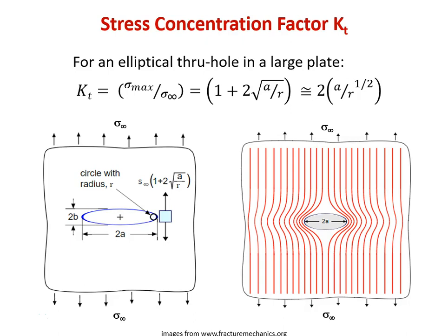So the ratio of the average stress over that whole big thick plate, sigma infinity, to the stress right at the edge of that elliptical hole is defined as K sub T, called the stress concentration factor. That's defined, of course, as sigma max, the stress right next to that tighter radius on the ellipse, over the average stress over the whole plate, sigma infinity. And that's equal to 1 plus 2 times the square root of a, which is the long radius of the ellipse, over r, which is the radius of curvature right at the tight radius of the ellipse. Of course, if a equals r, we have a circle instead of an ellipse, and we go back to the formula that we had for the circular hole on the other page.